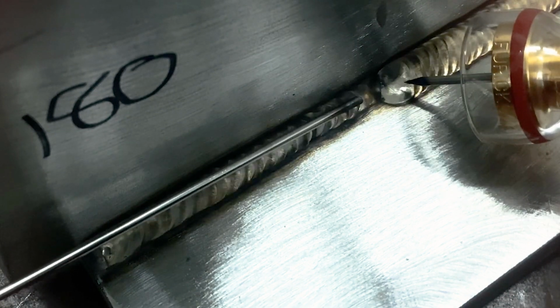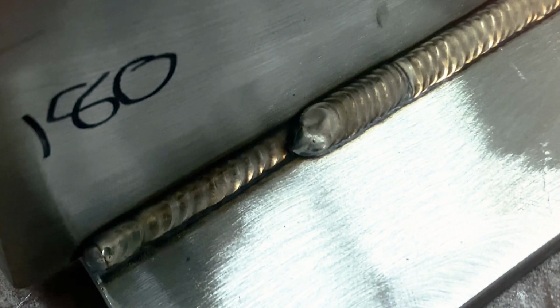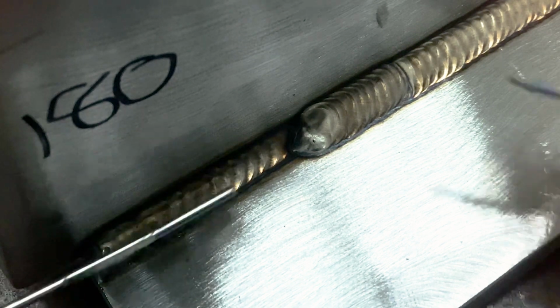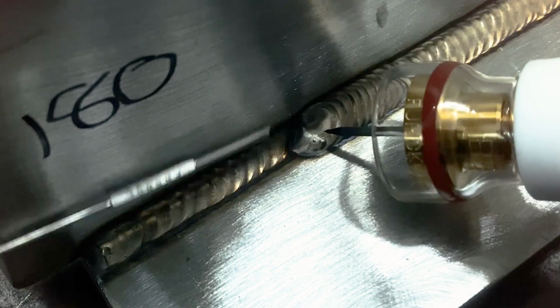Again, stepping it up to 180 here. I'm using the same technique, same arc length, same everything. You'll notice if you watch the edge of the weld, that puddle's really starting to bounce back and forth. And then I had to stop, regather myself, and grab a new piece of wire. But you'll notice if you watch the edges of the weld, I'm really having to move faster, and I'm having to apply more filler, more wire into the puddle, if you will, to make sure that that puddle is happy, right? To avoid undercut, to avoid it getting really out of control.